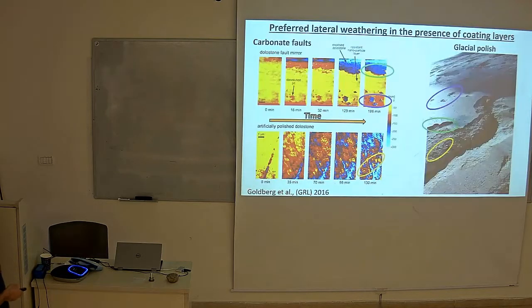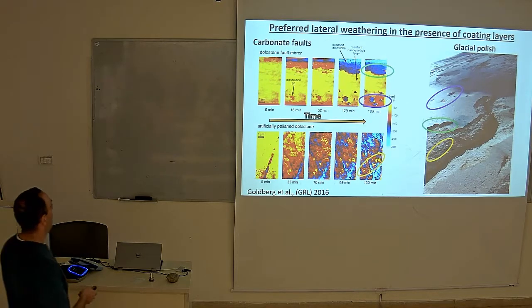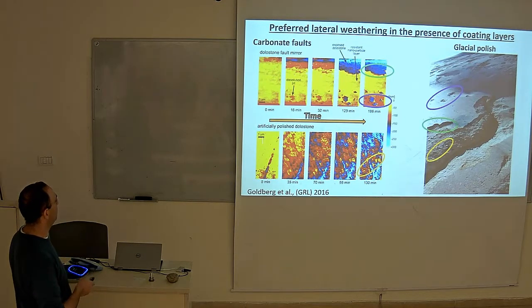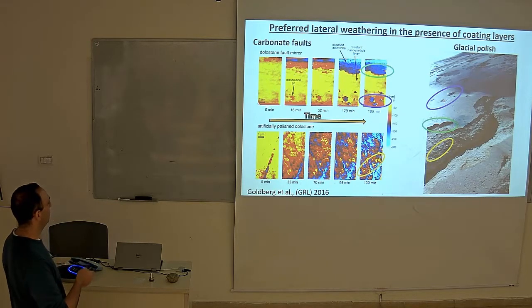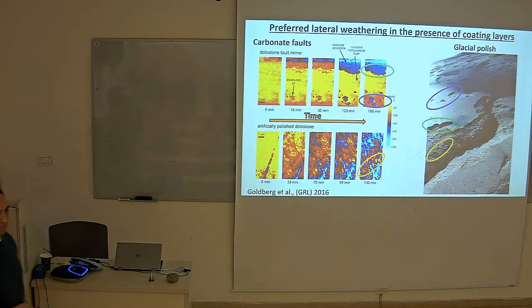What we get on a larger scale is lateral evolution and weathering of this pit, and we get these pits. A nice comparison is what Ron Goldberg did in his master's with Simon and Emmanuel, an experiment with AFM. So it's totally different scales from the glacial polish. This is 1 micron here. And he started with a polished surface from a dolomite fault mirror and a manually polished surface of the same dolomite fragment. Then he exposed it to water flow, scanned it under atomic force microscopy, and looked at the evolution of the topography.